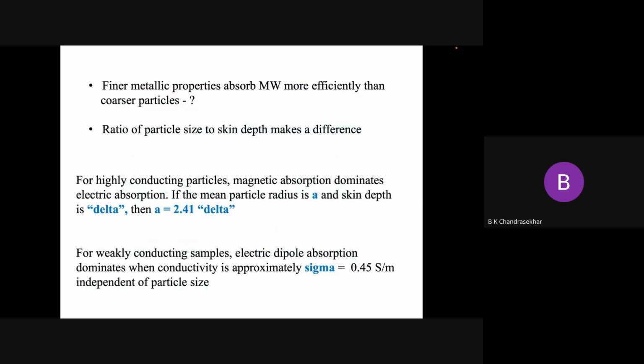Normally, it was felt that finer metallic particles absorb microwave more efficiently than coarser particles. But this was the original thought earlier, but that is not the case anymore. What they have found out is the ratio of the particle size to skin depth is the one that controls whether a metallic powder can be heated or not. Okay. These developments of theoretical calculations and modeling has helped us in understanding how the microwave interacts with materials.